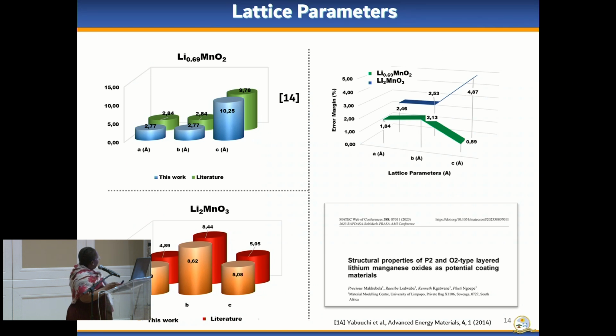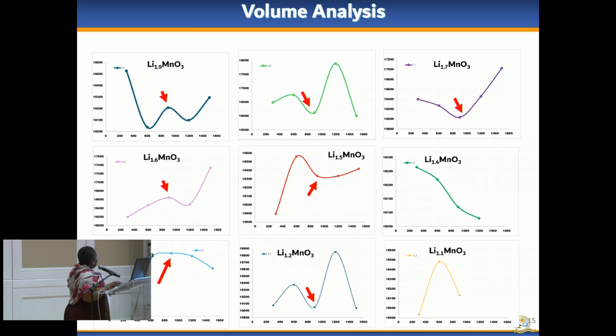In terms of lattice parameters, we did DFT work on both the core and the shell, and we found that the error margin for our lattice parameters is within 5%, which was a very good agreement. Then we proceeded to do molecular dynamic simulations, and here we're showing the volumetric analysis, during which we found that there was one particular temperature during which a lot of fluctuations were happening, and this was around 900 Kelvin. But we couldn't figure out exactly what is happening, because this was occurring in all the different concentrations from Li 1.9 all the way up to Li 1.1.